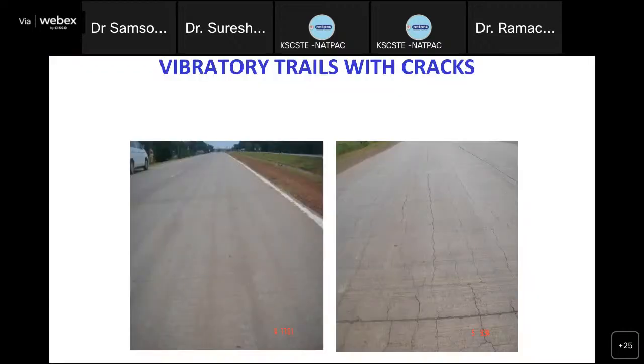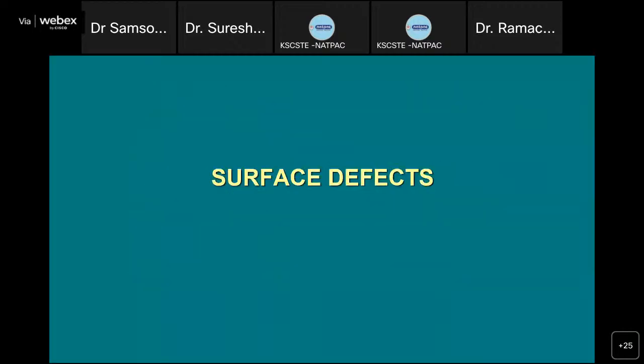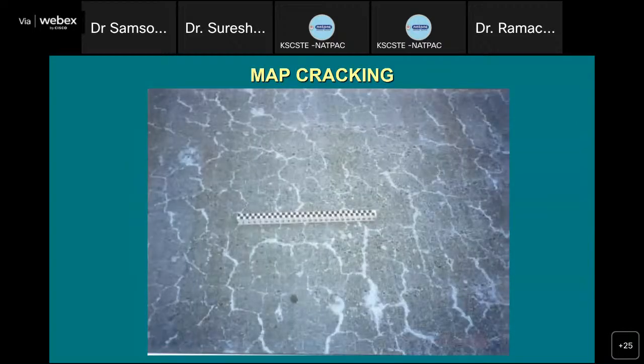Now let us consider the other types of distresses. Let us take one after the other. The surface defects. Now this is called a map crack. There is no pattern to this. This is called map cracking or plastic shrinkage cracking. Whenever concrete is laid with a very high dosage of admixtures, and the day temperature is quite high, you will see these surface cracks. What happens is, because the water cement ratio is low, the water at the surface evaporates very fast, and that makes the surface dry, and that results in these surface cracks or map cracking or plastic shrinkage cracks.